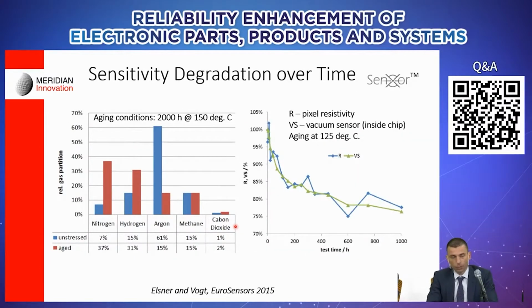Another major concern is, as I said, the interaction with the getter and the overall change in the sensitivity or response function over time. Again, an example of a microbolometer here shows degradation over an aging period of 1,000 hours. Approximately 20% of the sensitivity is lost. What that means is if you today calibrate your sensor and you're able to accurately detect the ambient temperature and probably a person's skin temperature, then in about a few months or a year, you will be underestimating both these temperatures. That's clearly not acceptable. So we're looking for ways to assess the amount of loss that we see in our process, and also how to counter that.